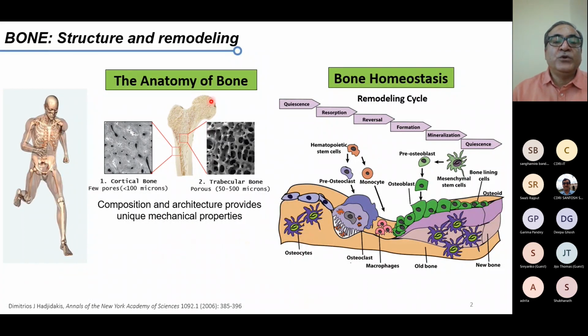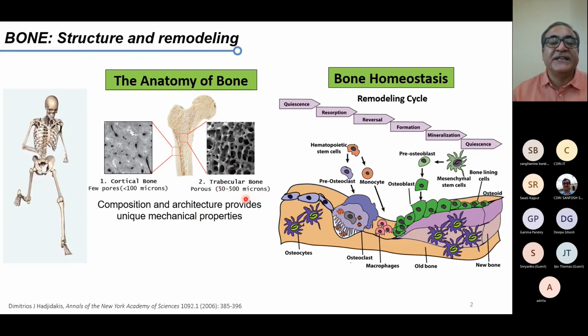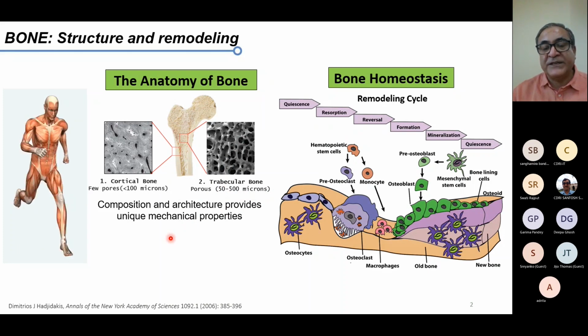If you look into the bone anatomy, you have the hard part, which is cortical bone, the strongest part of the bone, with few pores, less than 100 micron in size. Whereas the cancellous trabecular part is more porous and a bit weaker in mechanical property, with a more porous structure between 50 and 500 micron. That composition and architecture provides the unique mechanical properties.